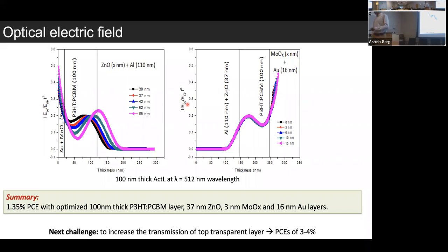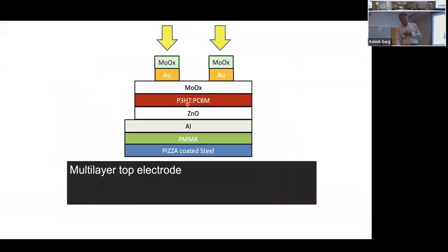We have only 39% transmission, which means 60% of the light is not going to be absorbed. What is the benchmark efficiency of P3HT-PCBM? We chose P3HT-PCBM because it's a workhorse material. Although it's not a high efficiency material, it helps us optimize the processes. So how to increase the transmission was the next goal, because you're still losing 60% of light. With 100% transmission, you get about 3%. With 50%, you should get about 1.5%, and you get about 1.35%. So the question was, how do you increase this efficiency by increasing the transmission?